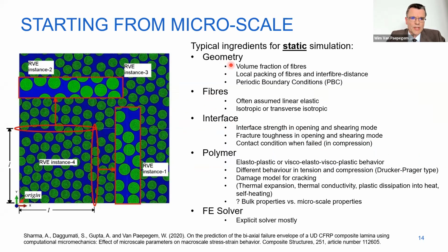First of all, about geometry. We need to define a volume fraction, which is consistent with the experiment. We have to decide about the local packing of fibers and also interfiber distance. The closer the fibers together, the higher the stress concentrations will be. And we need these periodic boundary conditions. And here you see exemplified, here you have one instance of your representative volume element. Here is zoomed in the boundary of this representative volume element. And you see that it matches perfectly with the adjacent instances.